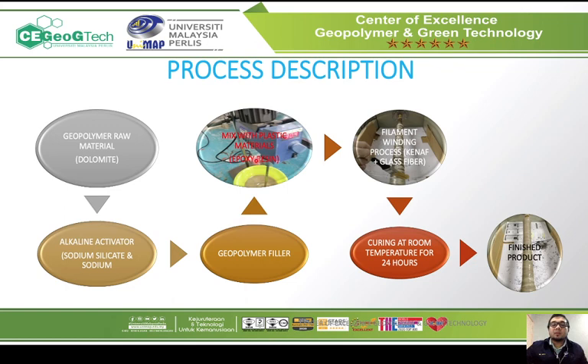And then after that, we mix the geopolymer filler with the plastic material, which in this product is epoxy resin. The geopolymer filler becomes the reinforcement in this plastic material. After mixing, we get the matrix resin, and we combine it with the filament winding process. In this hybrid GEOPIPE, I use kenaf fiber and also glass fiber mixed together with the epoxy geopolymer resin. After that, it cures at room temperature for about 24 hours, and then this is the finished product for this project.